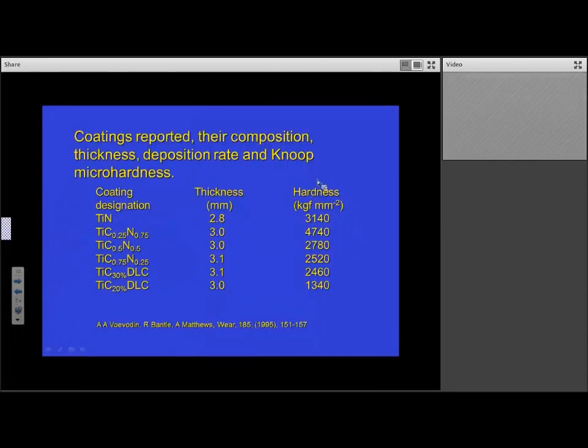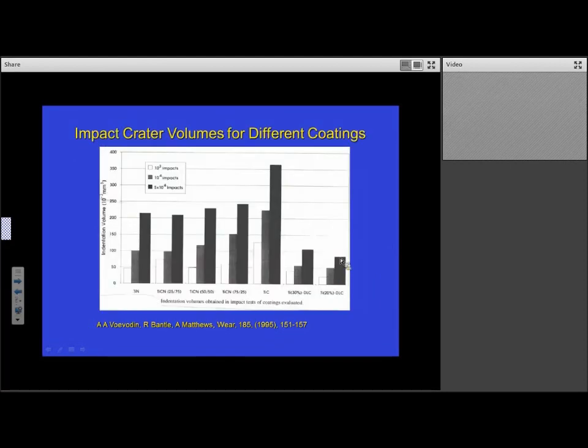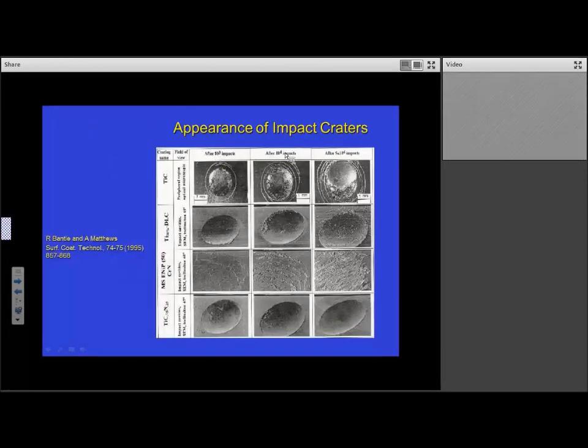Now next are some example performance using that impact tester going back some time now. Don't worry about what the coatings were, but just consider the hardnesses. They were all roughly 3 microns thick. Some of them were over 4,700 Knoop hardness, actually, in this case, and some of them were relatively soft. These were the titanium carbide diamond-like carbon coatings. And what you find in that impact test is the coatings that gave the best impact resistance, the lowest impact volumes, are the more elastic, less hard coatings. And this is really brought out best when you look at the indents after 1,000 impacts, 10,000 impacts, 50,000 impacts.